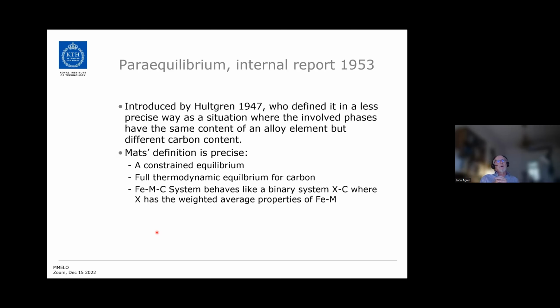The para-equilibrium as a concept was introduced by Hultgren some years earlier, and he defined it as a case where the growing phase had the same alloy content as the parent phase, but different carbon content. So it was not a very precise definition. But Mats's definition is precise. It is a true thermodynamic equilibrium, but it is a constrained equilibrium. So it's full thermodynamic equilibrium for carbon. But this Fe-M-C system, iron, an alloy element M, and carbon, behaves like a binary system, X-carbon, where X has the weighted average properties of iron and M.